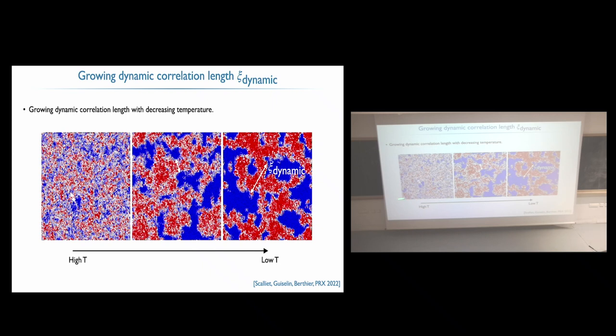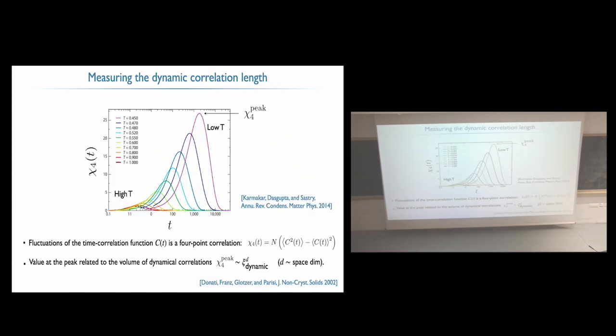So at high temperature, when the liquid is still very fast, you don't have so much heterogeneity. And then as you cool the system, you get some length scale, which is describing the dynamics, which increases. And this is something that you can also measure both in experiments and simulations. And the way people have been doing that is via this 4-point function. So I'm introducing this now because Misaki will talk about it in a recent model afterwards.